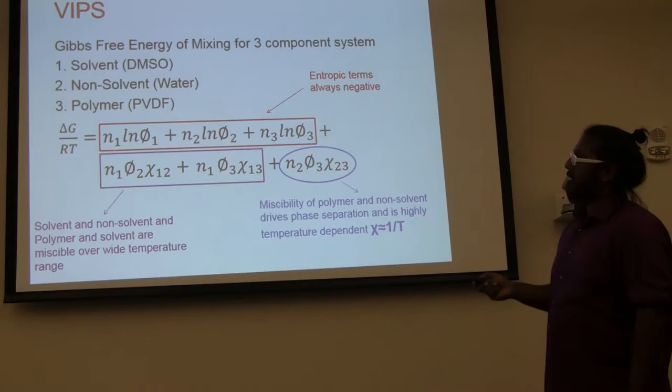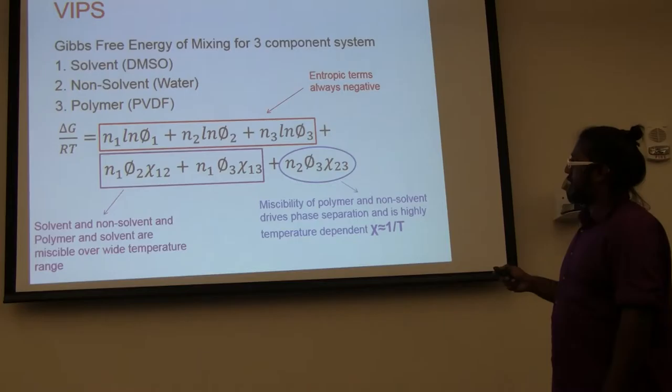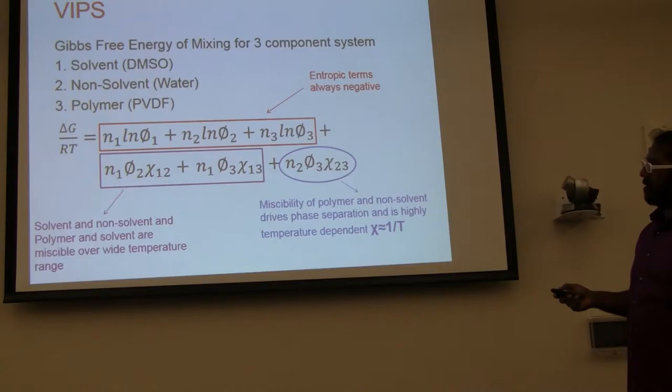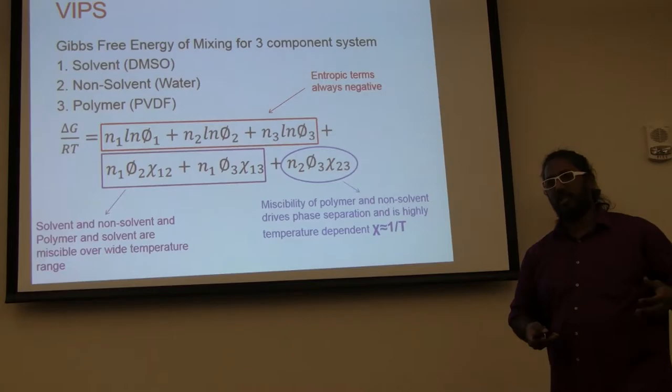Vapor-induced phase separation is a thermodynamic process. It's really governed by this equation right here, which gives the free energy of mixing. What you really need to know about this equation is that if this term is positive, things will phase separate. If this term is negative, things will mix. These first three terms here are always negative. No matter what, for any system, always negative. So these will always lead to mixing. These two terms can be positive or negative.